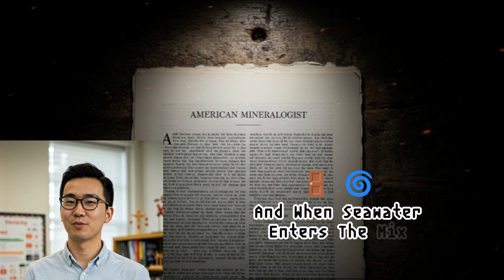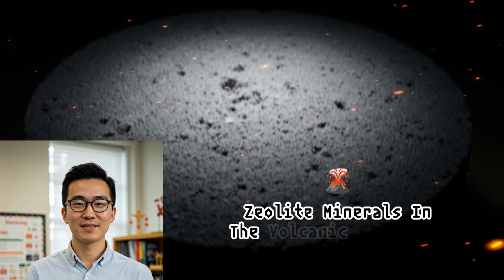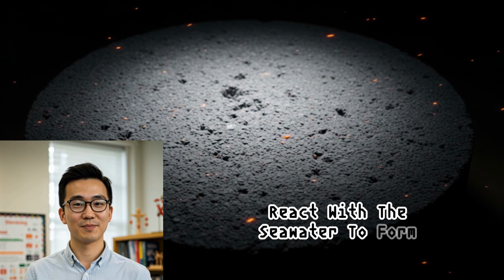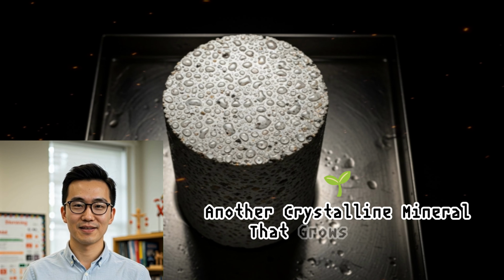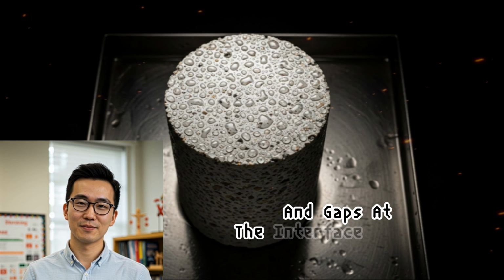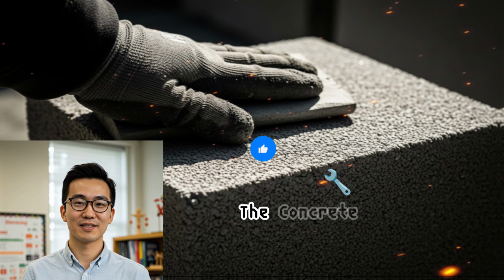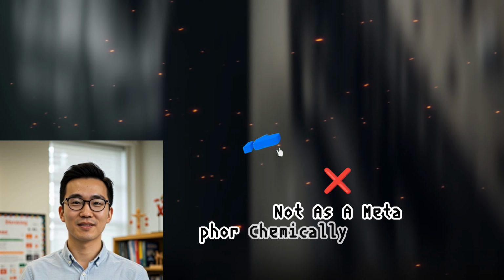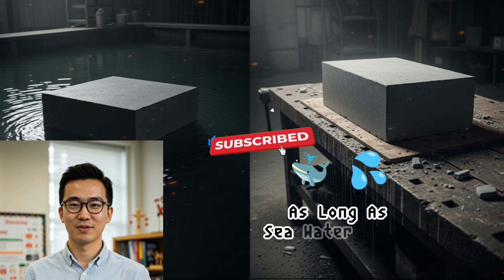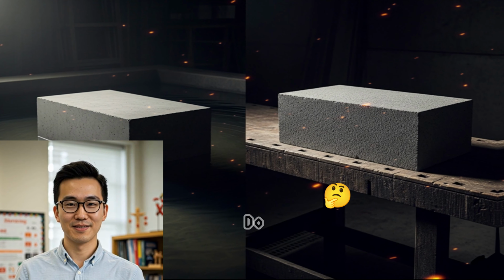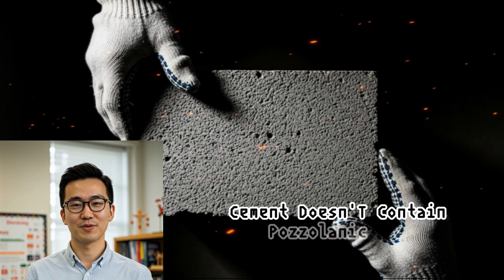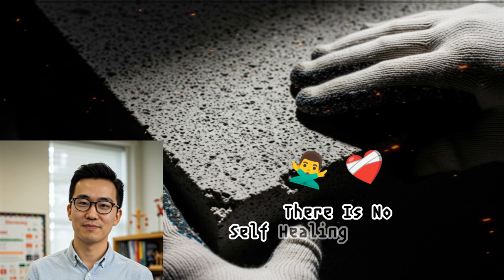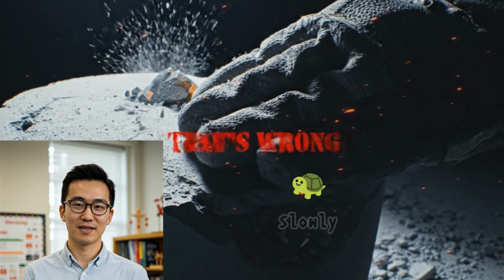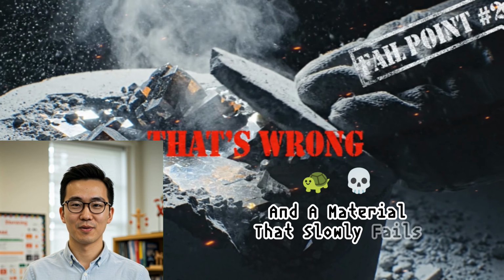And when seawater enters the mix, the aluminium-rich zeolite minerals in the volcanic aggregate react with the seawater to form phillipsite, another crystalline mineral that grows outward, plugging voids and gaps at the interface between concrete and ocean. The concrete repairs itself, not as a metaphor, chemically, continuously. As long as seawater keeps entering, the reaction keeps running. That is what modern concrete cannot do. Because Portland cement doesn't contain pozzolanic ash, and without the ash, there is no tobermorite reaction. There is no self-healing mechanism. There is just a pH that slowly drops and a material that slowly fails.